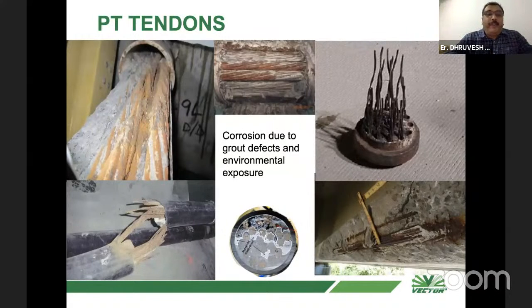These photos may be of external PT or some PT which are not of a bridge, but they give you a glimpse of what happens. Like the left-hand side photo, the top one has voids and corrosion happening. The left bottom one shows corrosion, you can see that white color thing. This is because of chlorides, and the tendons have broken. The end cap has broken on the right top side. And the middle photo is basically because of segregation of the grout. We'll talk more about all these things.